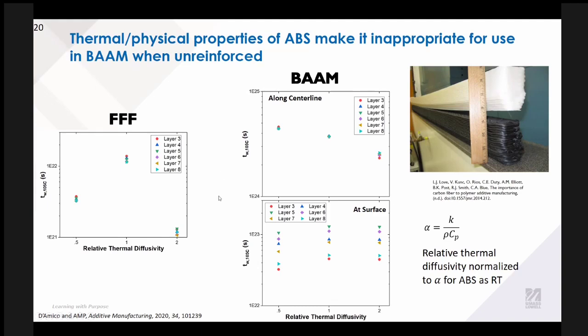And so this suggests for BAM that probably the chopped carbon fiber is stiffening the structure, and that suggests that other reinforcements could be used, that the thermal properties don't matter as much for that warping, since what the fibers are doing is resisting the warping. So that was kind of an interesting finding.